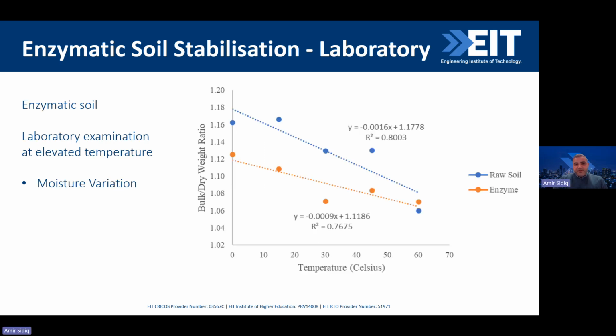Then, using the enzyme and the raw material, I tried to identify the moisture loss within the raw material and the moisture loss within the enzyme material. So you can see the moisture as a gradient. The moisture is getting lost at a much higher gradient in the raw material compared to the enzyme material.